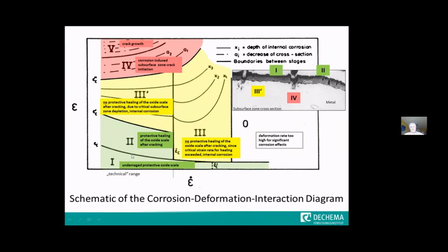Now, of course, the first stage is that the protective layer may crack, the protective scale. Stage number 1 means we move from the still intact scale to a situation where the first cracks can be formed, as you can see here. So this is a critical strain. Once this strain is reached, cracking occurs. And if we are below the critical strain rate for crack healing, then the protective effect can be restored.